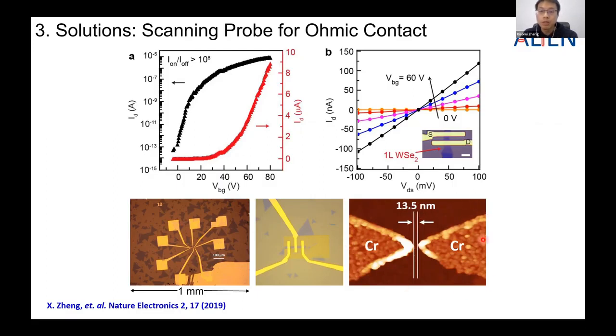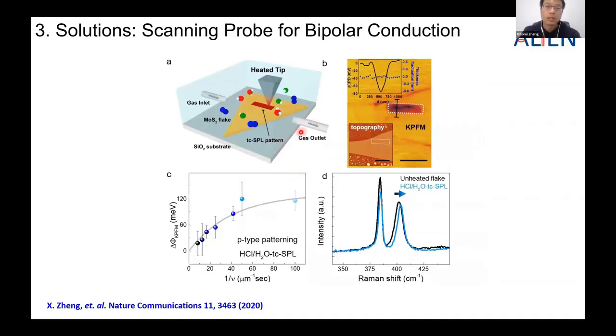This is a simple liftoff method, and we are working on the hard mask liftoff method, which is supposed to give us resolution below 10 nanometer. Okay. So that's the first example, using thermal scanning probe to make good contacts. The second example I'm going to show today is using the same technique to dope the materials in order to achieve bipolar conduction.